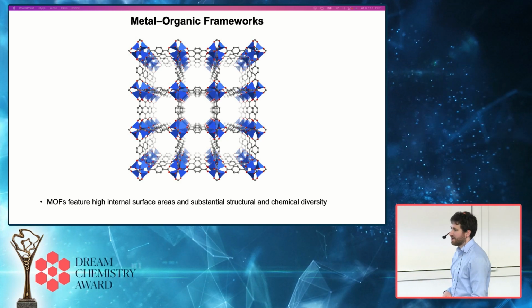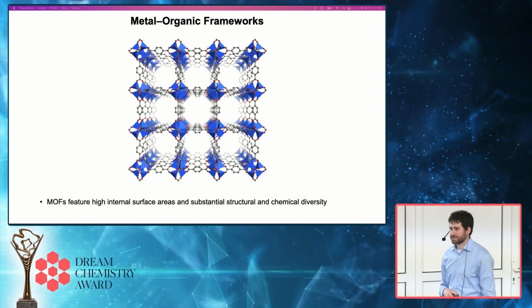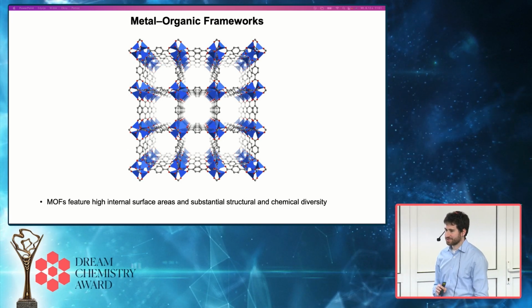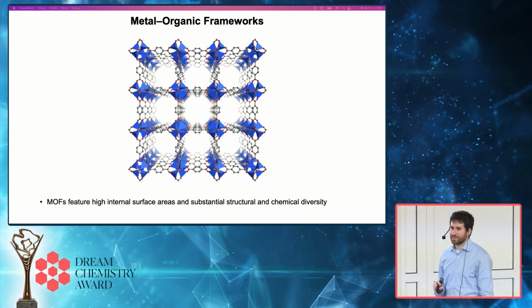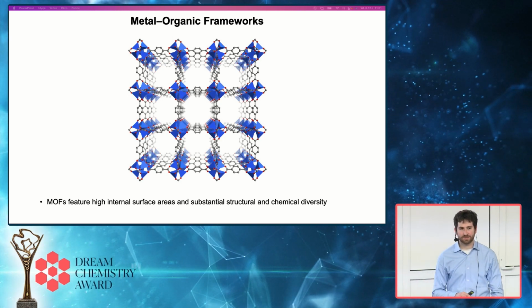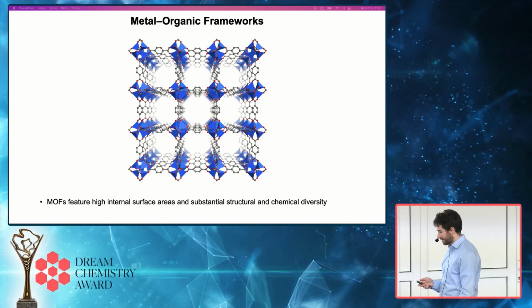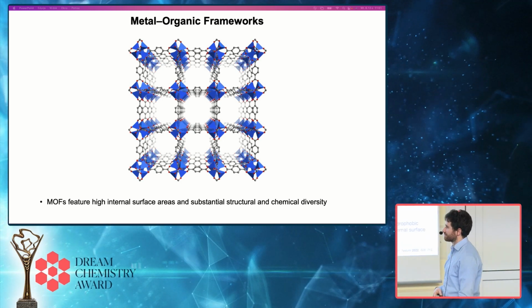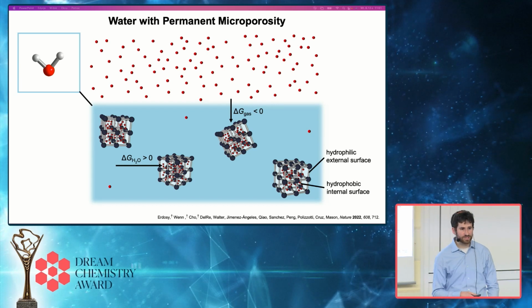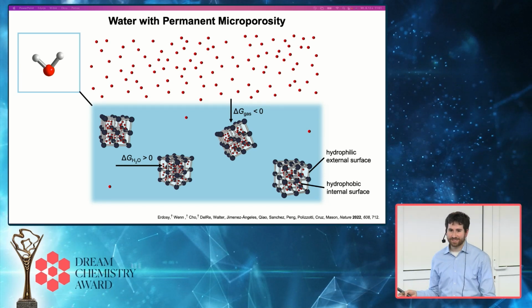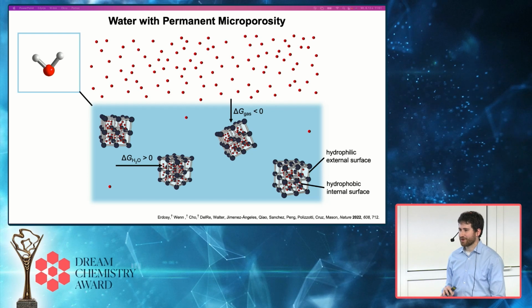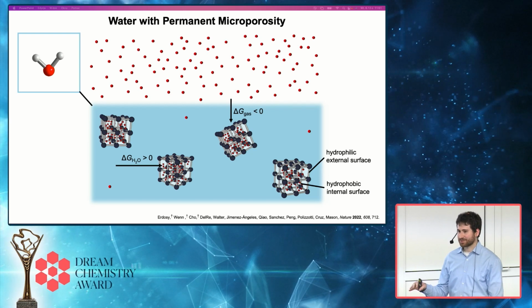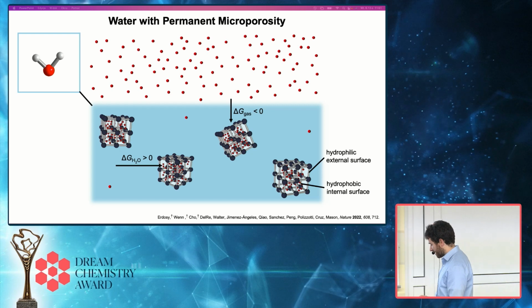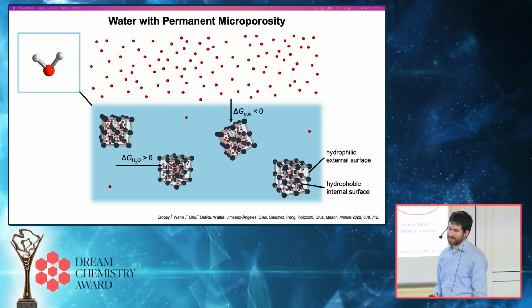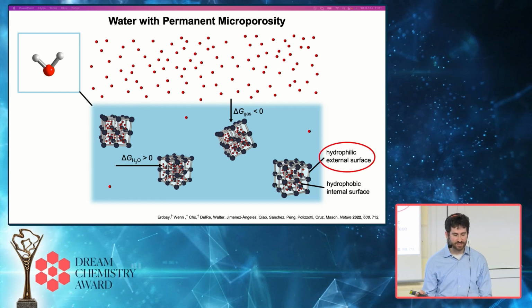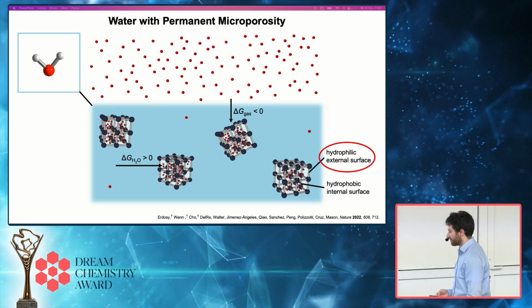And these materials exhibit much greater structural and chemical diversity than all inorganic materials like zeolites. So when one wants to tune biocompatibility, gas uptake and release properties, there's just a lot more that you can do with the MOF platform compared to other platforms of porous materials. The problem you run into with most hydrophobic metal organic frameworks is, one, it's hard to make metal organic frameworks that are hydrophobic enough to exclude liquid water. And two, any metal organic frameworks that are hydrophobic enough tend to have very hydrophobic external surfaces and tend to just aggregate in aqueous environments.